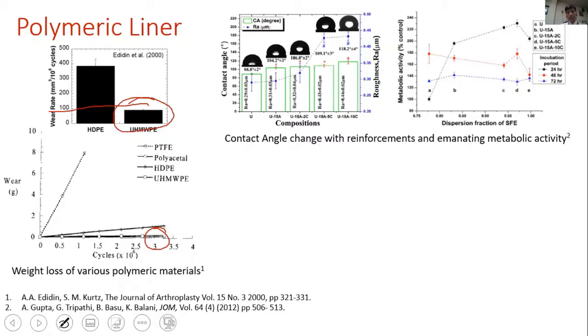But now we can play with the material itself by adding some reinforcement or additives, which will help us attain a different wettability. From that, I can also tailor what sort of biological response I'll get. If I want to deposit apatite, how can I do that by changing the surface free energy, even the dispersion component of it? If I add carbon nanotube, it starts to add to the dispersion component, and carbon nanotube being more active in nature, it starts to encourage the deposition of apatite in the biological environment.